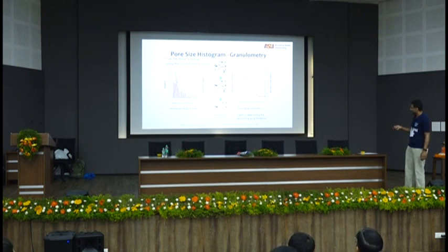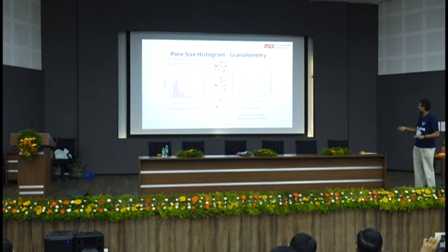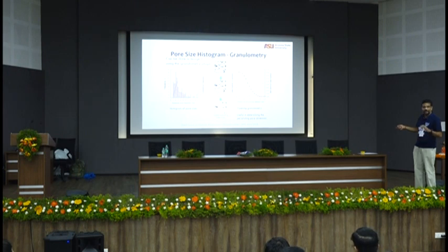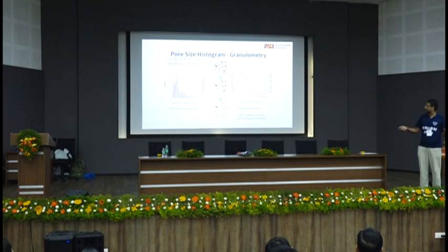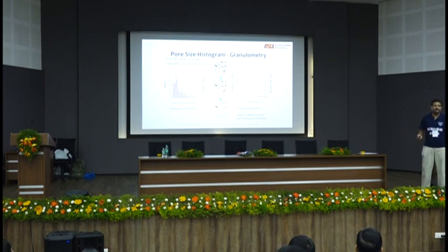So basically, I say I'm using a structuring element, typically a circle. I'm using a structuring element of 1 millimeter, which just means anything lower than 1 millimeter, I close. You see the difference between these two pictures? Anything lower than 1 millimeter, I've closed off, and I find out how much I have closed off. So this, I'm just showing 1 and 2 mm. But you can do for a range of sizes. I can do 0.1, 0.2, 0.3, 0.4. Again, image analysis very quickly done, right? Again, these are tools that you can very easily use.